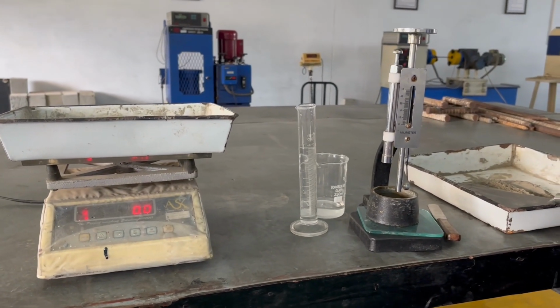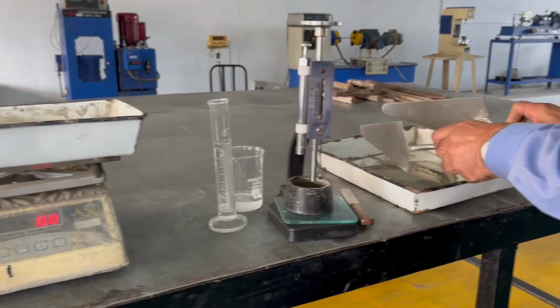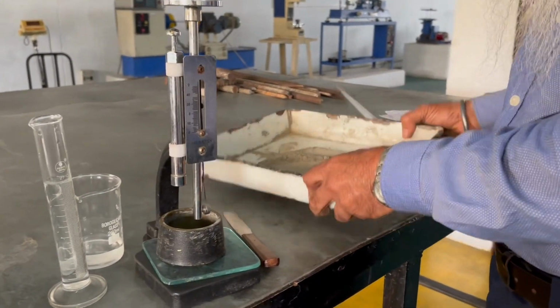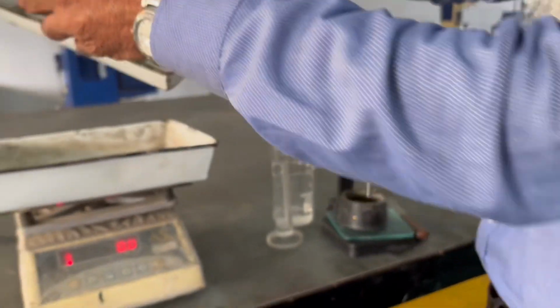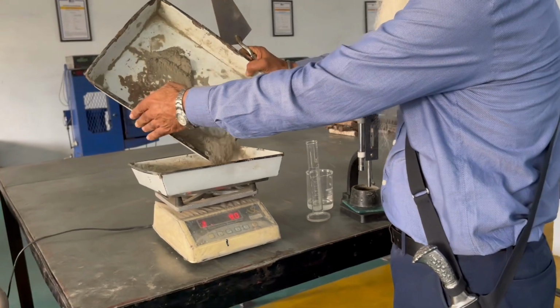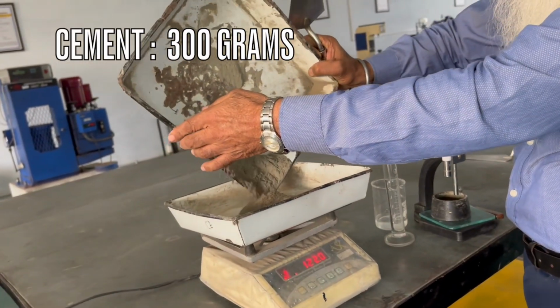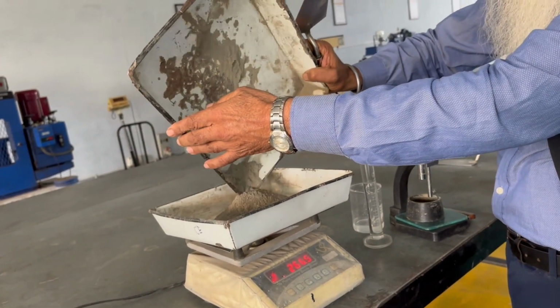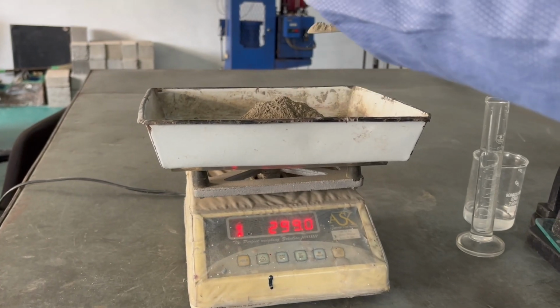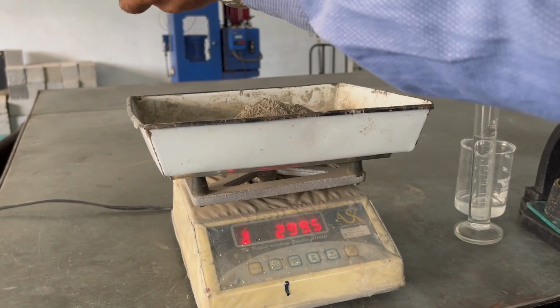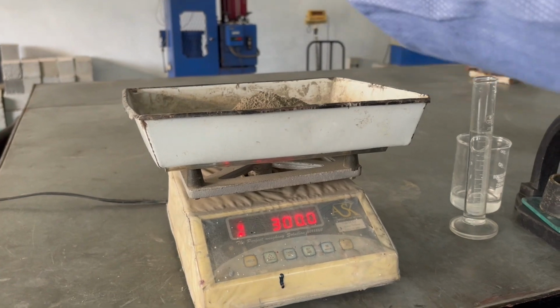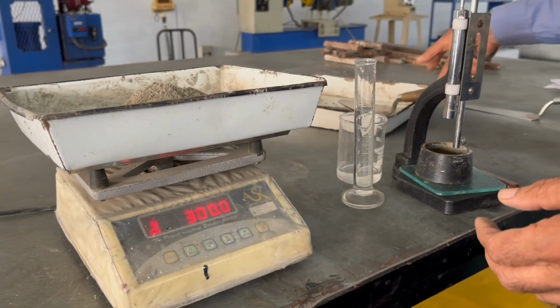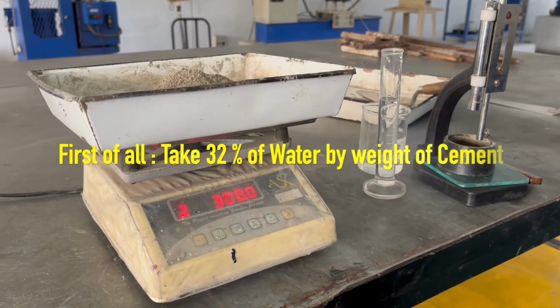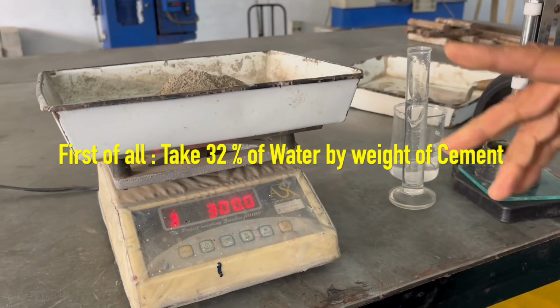First of all, we will take a known quantity of cement. We will take about 300 grams of cement. To take the exact quantity of 300 grams, then you can start to put the water. First, we will take 32% of water by weight of cement.